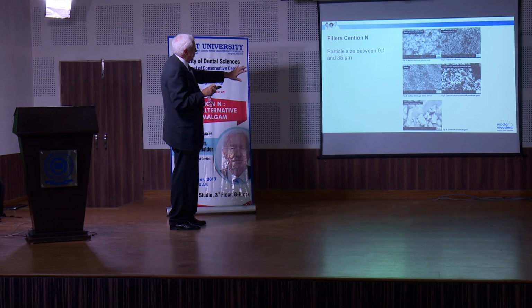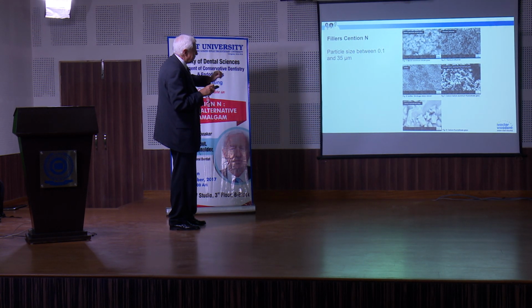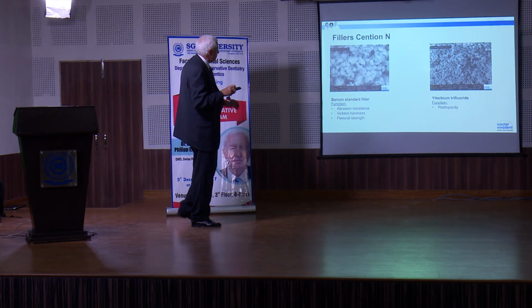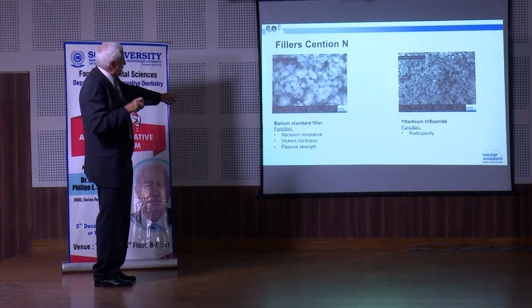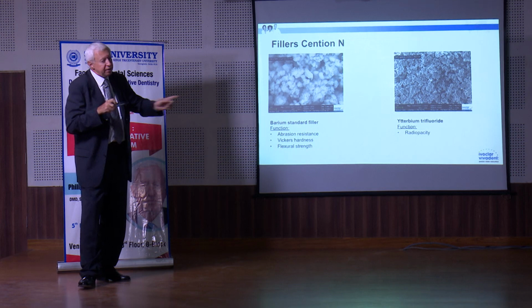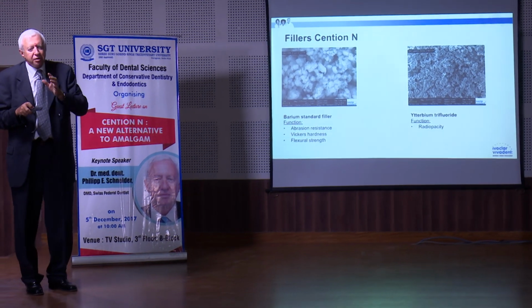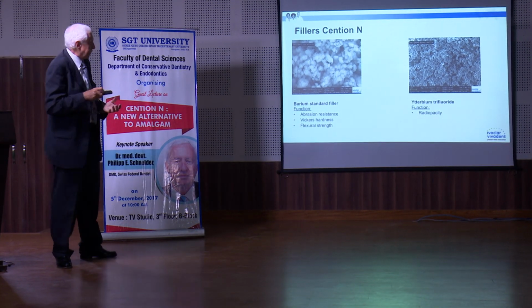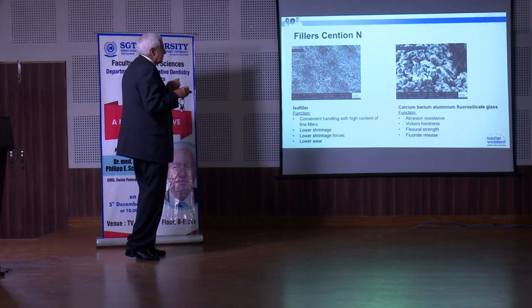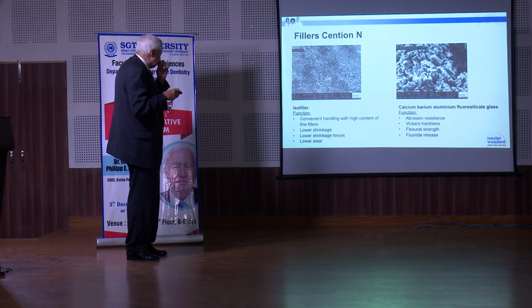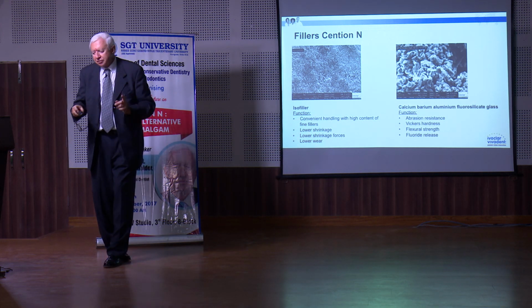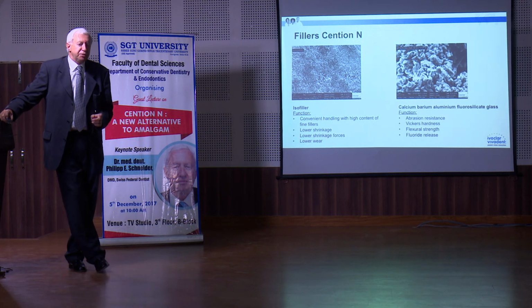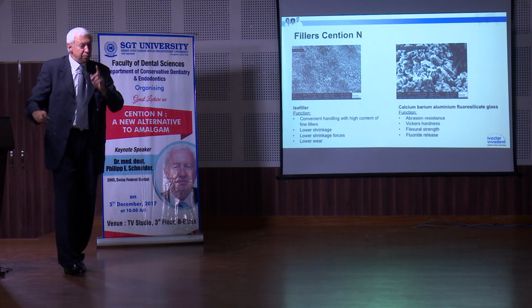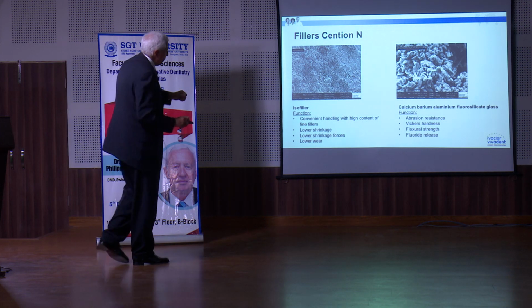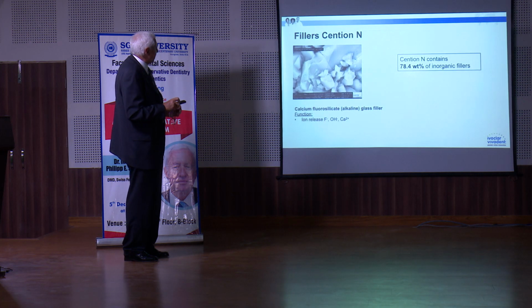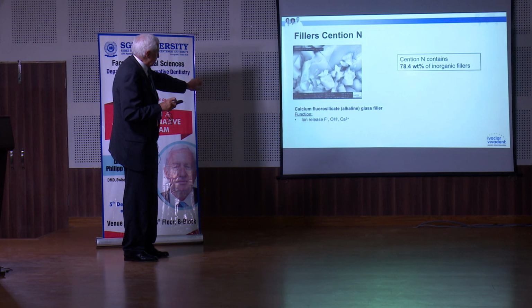Altogether we have 5 types of fillers. The particle size is between 0.1 and 35 microns. You see these 5 types. This one is well-known, barium standard filler. Ytterbium trifluoride has been invented by Ivoclar 25 years ago. It is really the best filler to represent the radiopacity. Then we have the isofiller. It is a pre-polymerized filler. This is really responsible for lower shrinkage. We have a shrinkage of this material of only 2.6% by volume. So it is really below 3%, and this is very good. Then calcium barium aluminium fluorosilicate glass, also well known. And at the end, our famous alkaline glass filler.